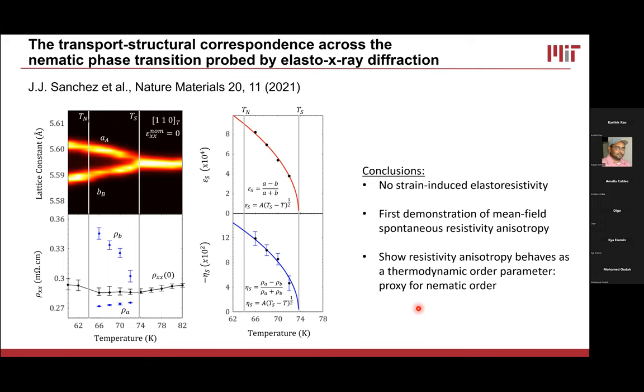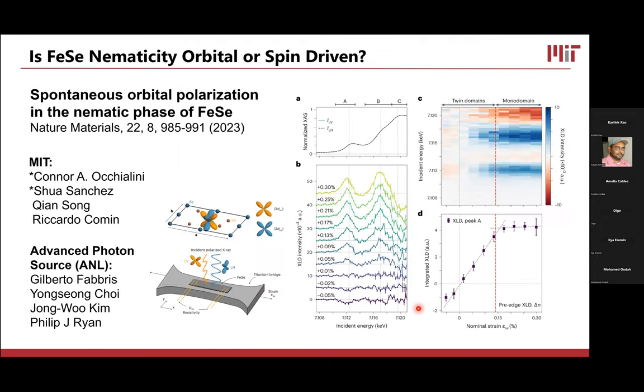Now, this was cool, but this transport measurement is not the same thing as making a measurement of the microscopic nematic order parameter. It's just a measurement of this transport proxy for the nematic order parameter. What I'm about to show you now in iron selenide is an advancement in this technique, where we actually can make a measurement of something that's very close to what could be the nematic order parameter, which is namely the orbital polarization. So this work now is building on the previous work. I'm going to use strain to detwin iron selenide, and then I'm going to use X-ray linear dichroism to measure the orbital polarization.